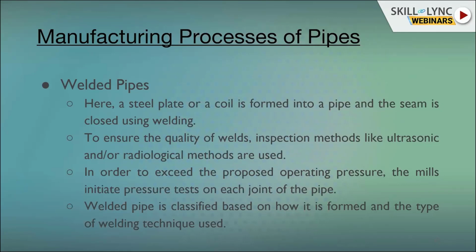In the hydrostatic test, we fill the pipe with water according to the diameter of the pipe, filling the whole pipe with water volume. Then we close the ends with end packing on the joints. Then we pressurize it to a particular pressure, for example through a reciprocating pump or a pressurization pump.